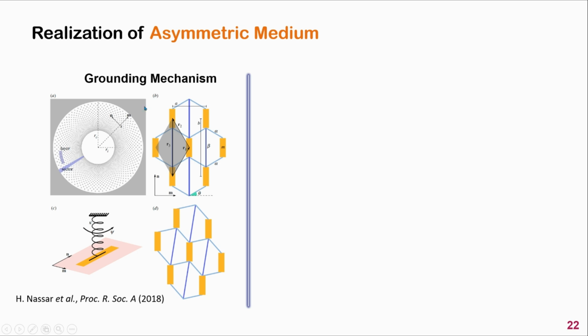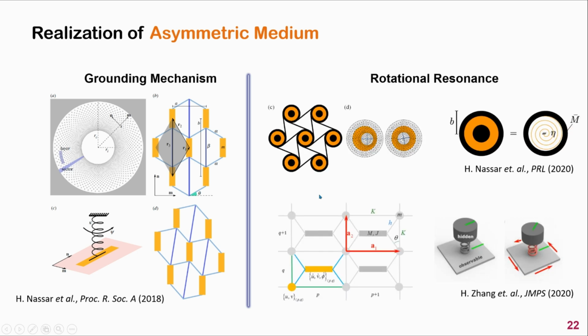Potentially, the necessary body torque can be achieved by utilizing grounded torsional springs as shown here. An alternative approach can utilize the rotational resonance effect. However, such an elastic cloak operates at a single rotational resonant frequency only and may not be applied to the static case. As shown above, since body torque is easily obtained in hard magnetic materials, can we exploit it to achieve elastic cloaking?